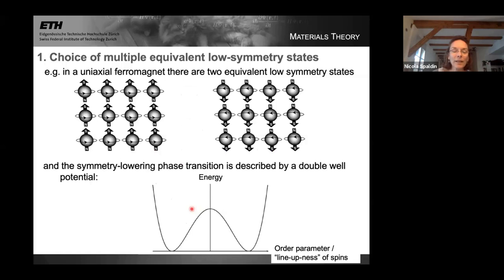The second feature, and when we say spontaneous, what that means is that there's a choice of multiple equivalent low symmetry states. And in the simple example of a ferromagnet, let's say a uniaxial ferromagnet, these could be the magnetization pointing up or the magnetization pointing down. These are equivalent, they have the same energy in the absence of a magnetic field. And the system could choose to go into either of these with equal energy.